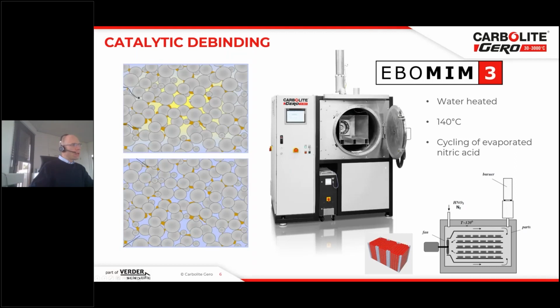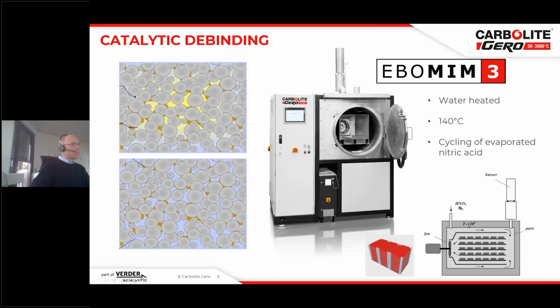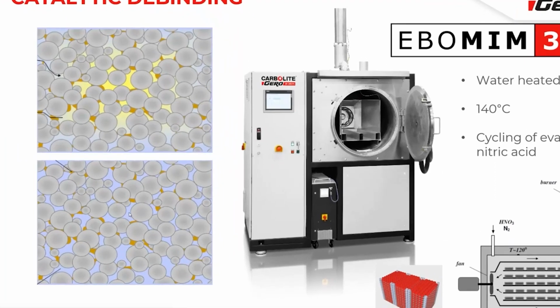So the only thing that vanishes now by HNO3 catalytic debinding is the yellow main binder. So you see the parts coming out of these furnaces. The main binder is now gone, but the backbone binder, the orange bars here, still remain inside that part.